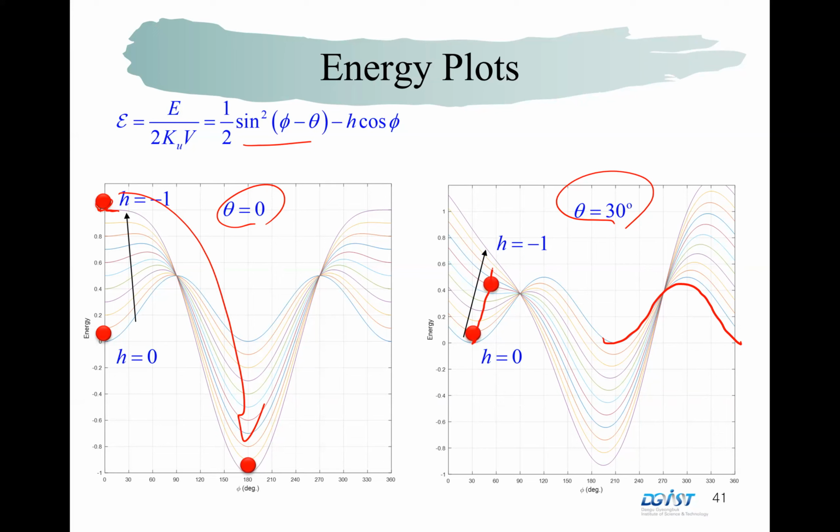So at the middle point, the direction of the spin, the magnetization, is not 30 degrees anymore, because the anisotropy energy favors one angle, but the field favors this angle, so the energy flips toward the other direction. So when we have this point, it becomes unstable, and it switches here. So we obtain a smaller switching field.